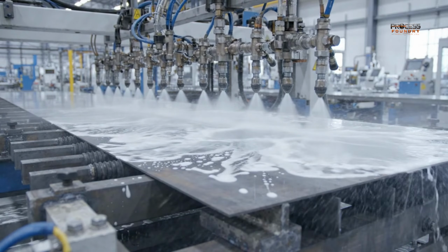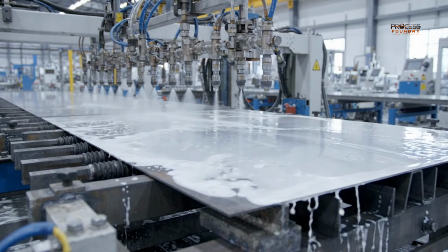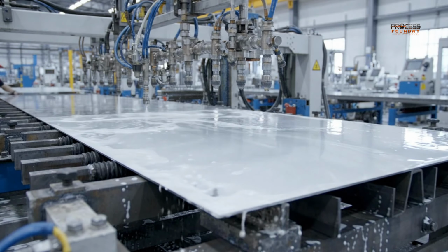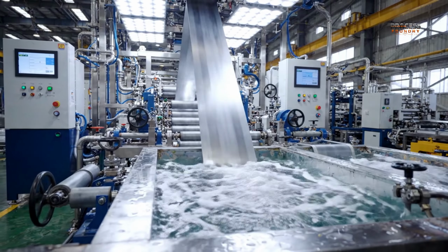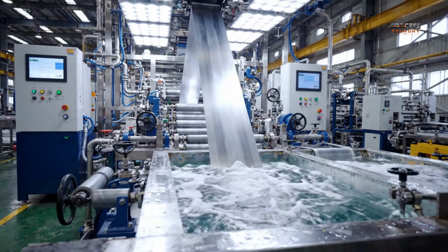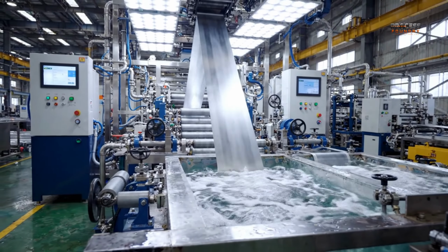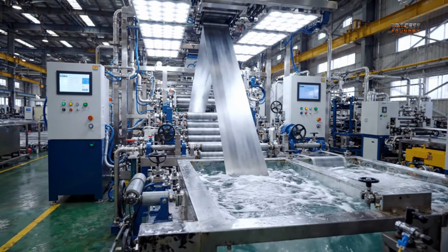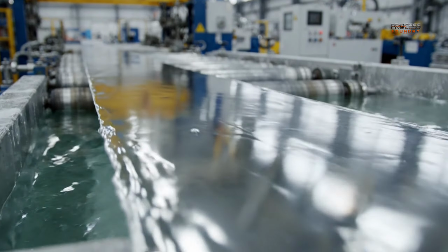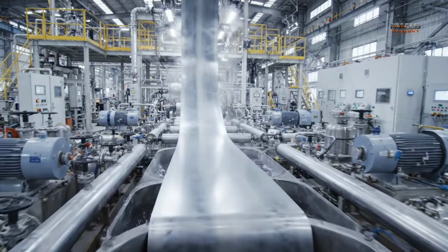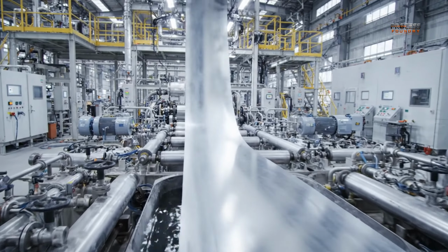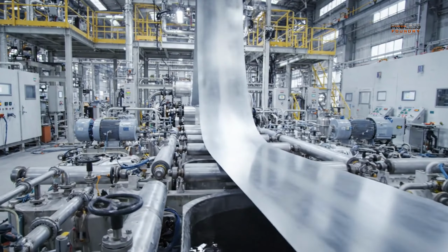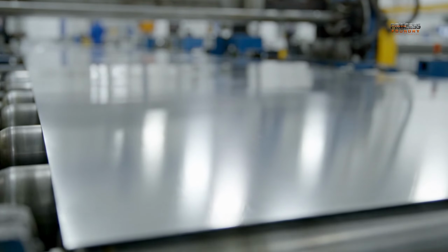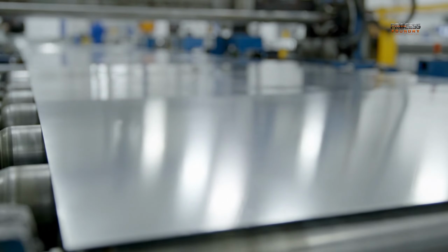It glides through a mild acid pickling chamber to completely clean off any metal dust. Then the steel strip submerges into a highly sophisticated electrolytic plating system. Here, an ultra-thin layer of pure tin tightly adheres to the metal surface. This armor transforms the steel into a perfect food packaging material, absolutely rust-proof.